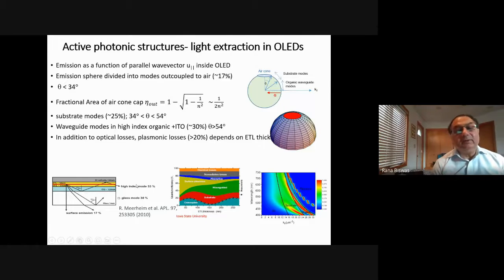Now, the problem in this device, it is actually very well known, is that if you look at the emission sphere, there's an air cone, which is the escape area. Then the light can only escape to the air side through this air cone, and this has a fractional area of 1/2 n squared. So this is only about 20%, unfortunately. Most of the light is trapped in substrate modes, which is about 20%, 25% or so, and a large fraction trapped in these waveguide modes in the high index organic layer.